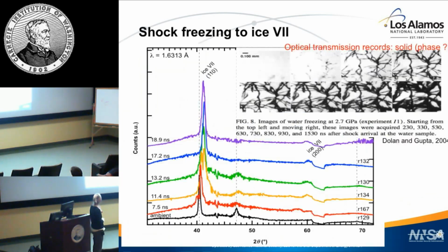Now we march as a function of time. So 7 nanoseconds, 11, 13, 17, 20. Over this period of time, the laser is on. I am pushing on my sample the whole time. And what we see is maybe at 7 nanoseconds, there's a tiny little shoulder. It's a little hard to tell. Tiny little shoulder pops up here, and there's some feature over here.